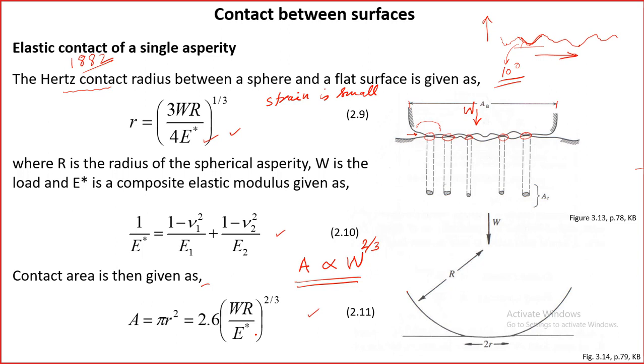The Hertz equation is very, very useful because there is almost no analytical way to find out the contact area between two surfaces under load. So basically we have to use the Hertz equation as long as the contact is elastic. We can also say that the pressure, which is W over A, is proportional to W to the power 1 over 3. And as I said earlier, for ball on raceway, for ball bearings, this part is taken as 2 over E star. So this is how this one will be written for ball on raceway.